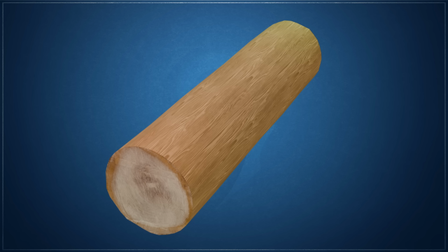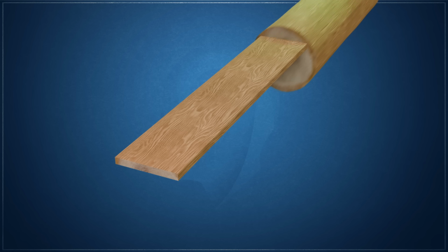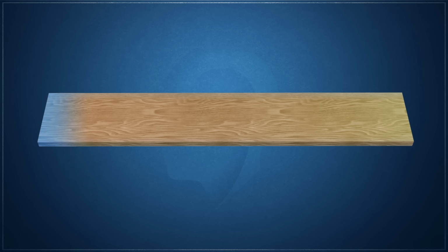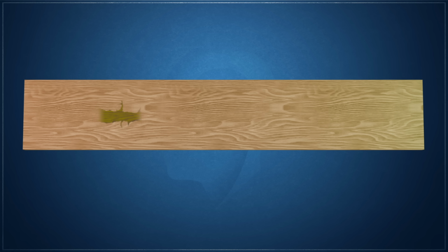Beyond its mechanical characteristics, wood's other physical properties are also highly directional. Moisture transport, for example, is primarily driven by capillary action through continuous cell lumina. Because these pathways run parallel to the tree's growth axis, liquid wicking is highly directional. Wood absorbs liquid through its end grain anywhere from roughly 100 to over 10,000 times faster than through its face or edge grain, with the ratio varying considerably by species. Electrical conductivity also follows a similar anisotropic pattern, with current propagating parallel to the grain with roughly 2 to 3 times the efficiency as it does perpendicular to it.